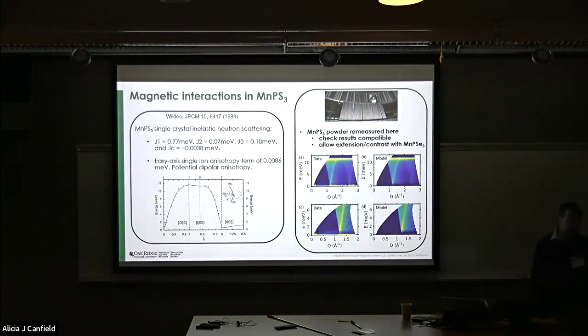For MnPS3, this was measured a long time ago, back in 1998, on a single crystal sample. Shown here are the exchange interactions they extracted. We were looking at the whole series with powders, so we started with what was known, firstly to see if we could reproduce the results. We collected these data on the Sequoia instrument. So here's the data. We plug these numbers into the model, and it's just a spin wave model, and you can see very nice agreement shown here.